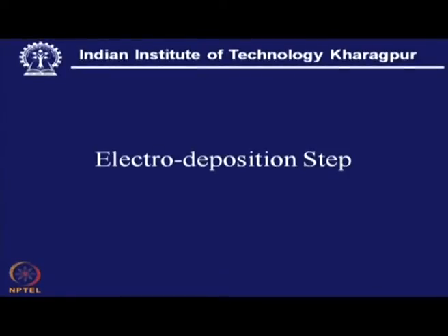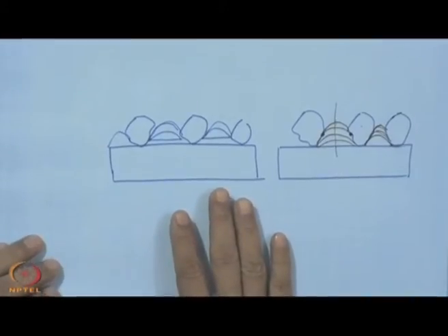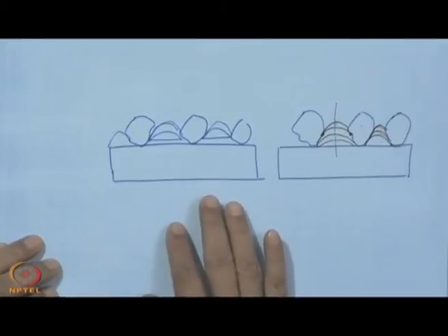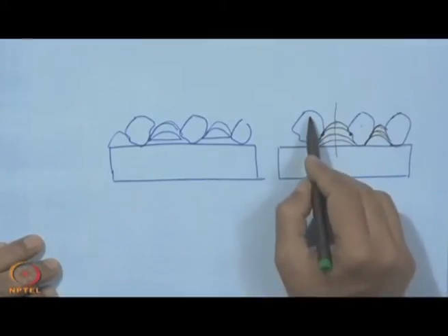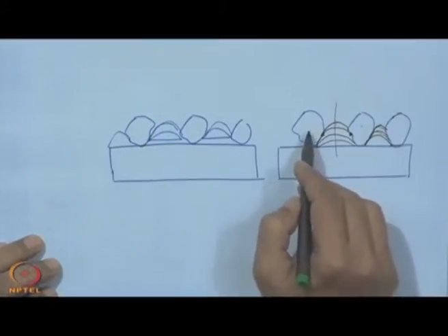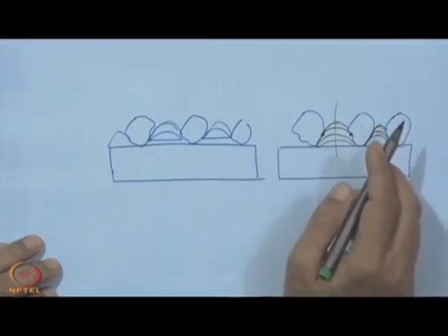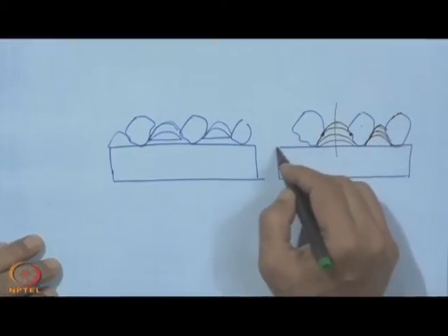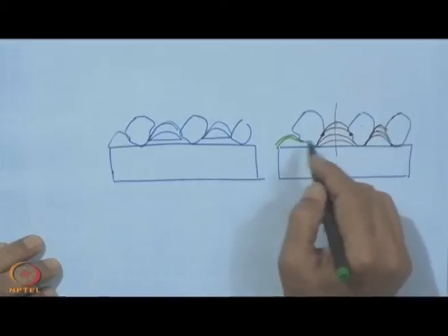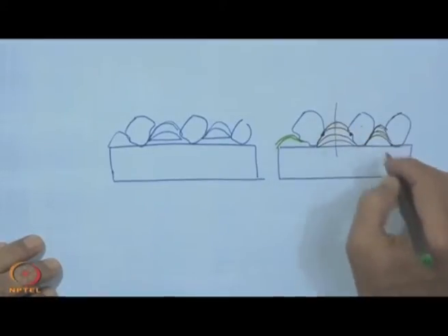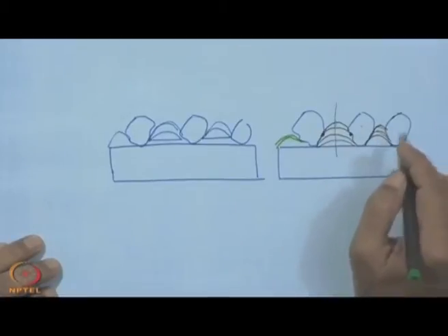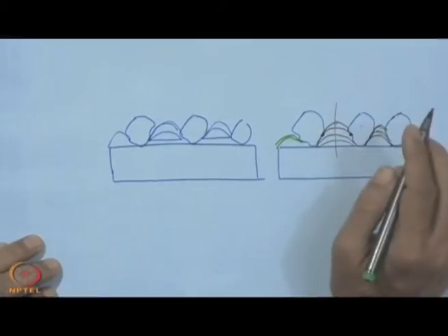So, this is actually the electro deposition step. With that we can grow the metal layer over this surface, and finally, the electro deposited layer will be ready for any abrasive action or grinding action. So, here actually these are anchored. This is just not a deposition as we understand by classical means, but it is the placement of the crystal, and then it is actually the deposition of the galvanic material, and it is holding by proper anchorage.